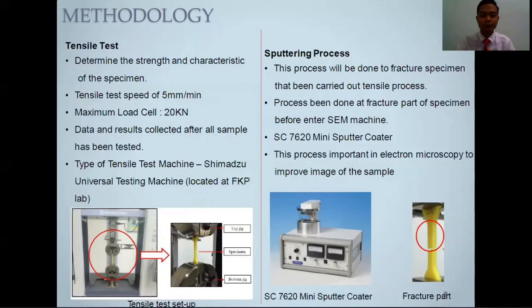The sputtering process will be done on the fractured specimen that has finished the tensile process. The sputtering will be done at the fracture part of the specimen. As you can see in the figure below, the fracture part is in the red circle. Okay, this process is important in electron microscopy to improve the image of the sample. The SC7620 mini sputter coater machine will be used for this process.